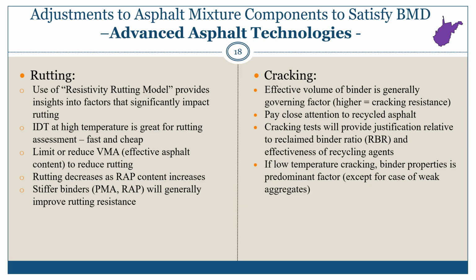From a volumetric standpoint and how to make some changes during mix design, if you want to improve rutting, look at limiting or reducing your VMA, essentially taking a little asphalt out. Rutting, he's found, decreases as RAP content increases as long as you're not adjusting it for a softer asphalt binder or a recycling agent. And generally, stiffer asphalt binders will help improve rutting resistance.